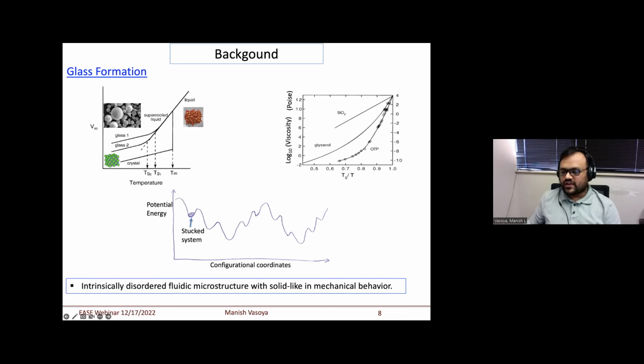Here there is no ordered microstructure; all atoms are located very randomly. Because of that, when you cool fast, your system gets stuck in some local minimum instead of going to the global minimum. Because it is stuck in the local minimum, its viscosity shoots up after the glass transition, almost on a logarithmic scale, as you can see here. So this microstructure is disordered, which means it's a fluidic microstructure, but it behaves mechanically like a solid because it can sustain stress thanks to the high viscosity.